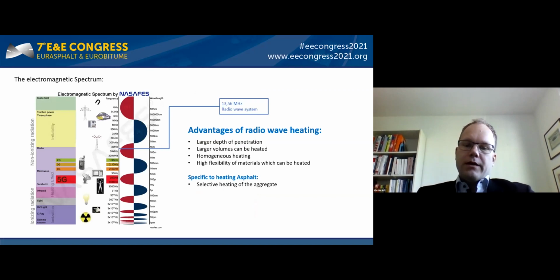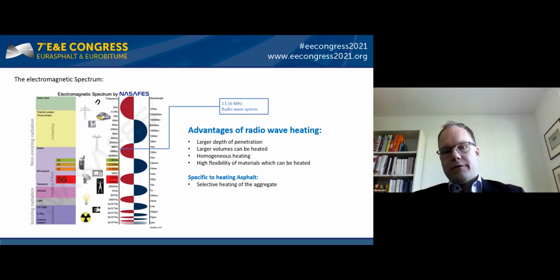So what is to be understood under radio wave heating? It is basically the same effect like in the microwave oven. You have a direct heat development in the materials, plus the advantages of radio wave heating compared to the microwave heating, that larger volumes can be heated due to another frequency which is used at 13.56 megahertz.